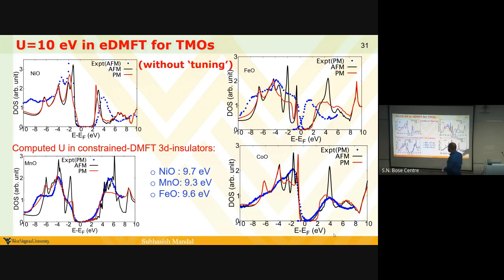And that is not published yet. We're working on it, and this is how we can compute the U for the two different phases of a material. Because the point is the screening mechanism is very different. Both for the early transition and late transition, the positioning of the holes, which are empty, is very different. So I'm a bit surprised you still get U equal to 10 eV, even if it is insulating. Probably because of the dimerization, there is something else that is happening.